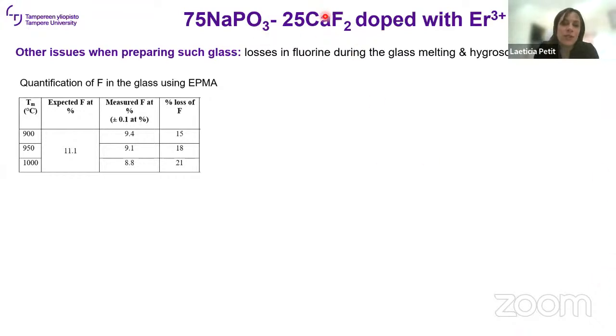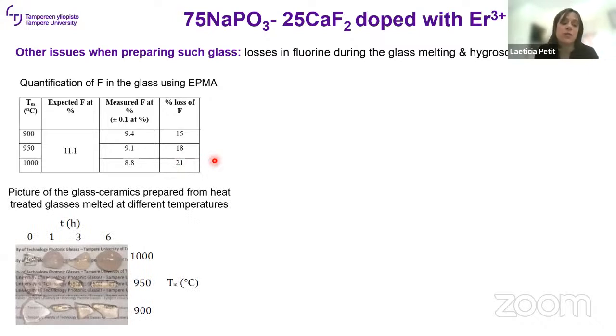We also have some other issues with this glass composition. The first one is the loss in fluorine. It's well known that fluorine is a volatile element. So we prepared the glasses using different melting temperatures, from 900 to 1000 degrees C, and then we quantified the losses in fluorine. And the reason I'm showing this is that the loss in fluorine has a huge impact on the transparency of the glass ceramic. All of them have this calcium fluoride crystal doped with erbium, but the transparency is completely different. So the crystal growth is different and depends on the fluorine content.